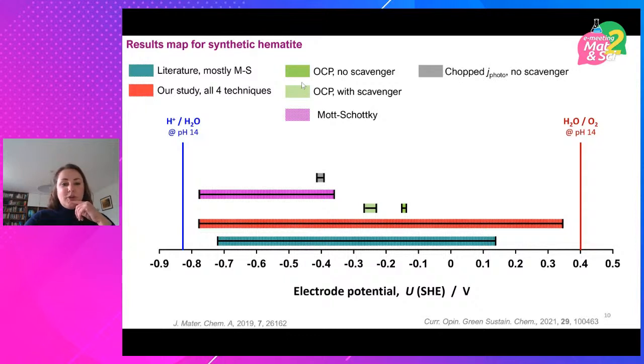Then we did chopped photocurrent without scavenger, which was more negative than OCP. So already we thought, well, the OCP values can't possibly be true. The ones that gave the most similar responses were the chopped photocurrent measurements. So at this point, we realized that transient measurements were probably the better way to go than steady state measurements.